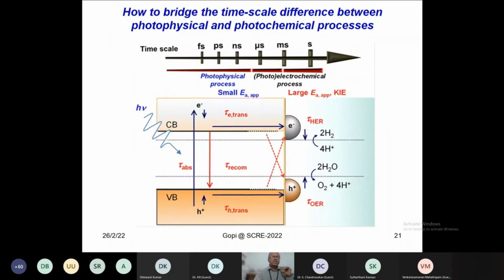This picture clearly shows that the blue arrows are the favorable arrows, and the red arrows are the unfavorable arrows. For example, the light absorption, again given in blue, and the electron excitation from valence band to conduction band, that's given in blue. So they're all good. But then the recombination is given in red. Recombination is not good because if electrons and holes undergo recombination, it is of no use.